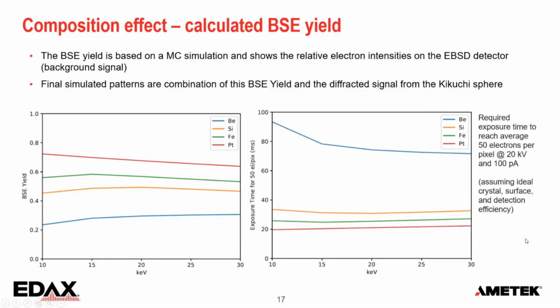And when we just translate that in how much we need at 20 KV beam energy, 100 picoamp of beam current, where we get about 50 electrons per pixel, then you can see that for platinum, we may need about 20 milliseconds to reach that intensity. And for beryllium, you have 90 to 95 milliseconds. So 4 to 5 times more time required for light materials.